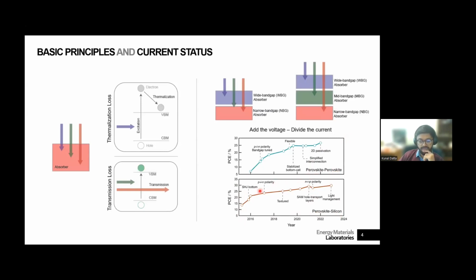So, for example, in the single junction space, the most efficient solar cells at that point were still the narrow bandgap NIP devices. But quite soon we realized that the PIN polarity is better in terms of optics, just because you lose a lot of parasitic absorption that you would otherwise have in the NIP devices. And then people have tried to work on textured cells, and then to reduce the optical losses further by self-assembled monolayer hole transport layers, and then of course light management.